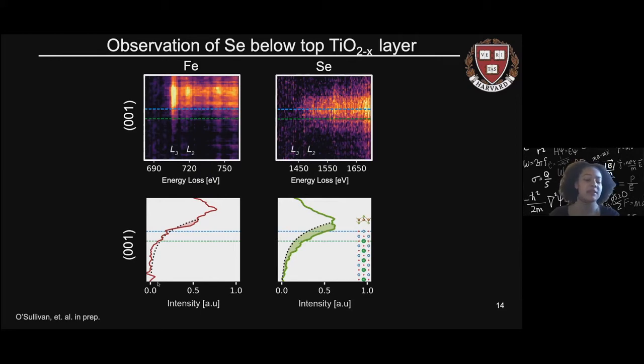You'll note that in both of these line cuts, we overlaid the black dotted line from the strontium line cut, as I showed on the previous slide. And this line is representing instrumental resolution, as I previously mentioned. So in effect, all of the selenium and iron signal to the left of this black curve, we attribute to simply being instrumental resolution, but we do find the signal to the right as significant, experimentally significant signal of iron and selenium. So as a result, moving forward, I'll be analyzing the light green shaded area between these curves, as opposed to the entire line cut itself.